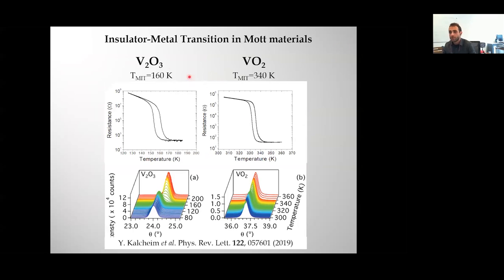So this volatile resistive switching is observed in materials that have an insulator to metal transition. They're normally referred to as Mott materials. And in San Diego, we work with probably the two most archetypical examples, which are V2O3 and VO2. So here you have resistance versus temperature. This is a logarithmic scale. And you can see that both have a first order phase transition in which the resistivity goes down several orders of magnitude. And together with this transition, there is a structural transition that happens at the same time.